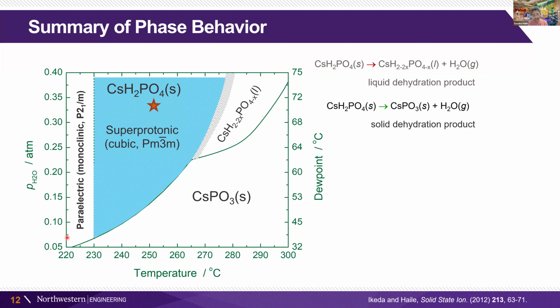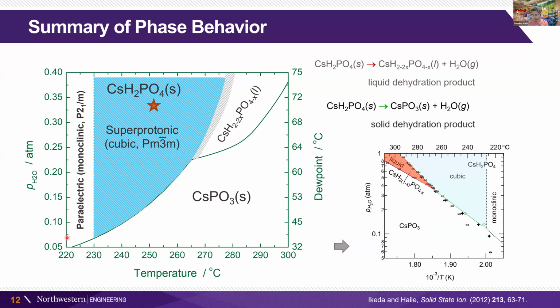And that explains why we had those two features in the thermogravimetric analysis measurements. We can convert this phase stability behavior into an Arrhenius plot and see that it behaves in a way that you expect, meaning that the lines all make sense, and we can take the slope of those lines to get at the activation energy, the delta G of reaction for these different reactions, and even confirm the value of the superprotonic transition temperature from the change in slope between the dehydration to the solid dehydration product from the monoclinic phase versus that from the cubic phase.